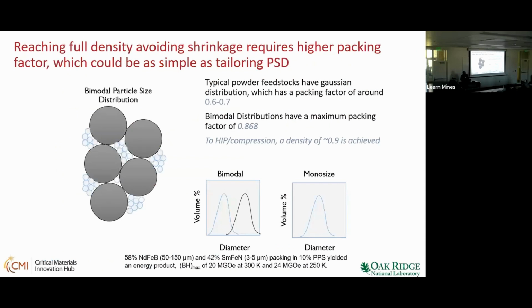Very recently, we worked with Ekina and the team on bimodal particles. With neodymium iron boron, the packing density is not going to be very high, like 0.6 to 0.7. If you mix it with samarium iron nitride, that's where we do the bimodal approach. You can take dysprosium-free neodymium iron boron mixed with samarium iron nitride. Samarium iron nitride magnets are made of small 3 to 5 micron particles. Neodymium iron boron is always 45 microns or higher, almost 100 microns.